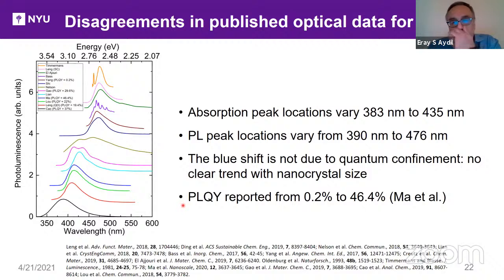So the absorption peak locations vary from 383 to about 435 nanometers. Photoluminescence is also the same. Here is photoluminescence coming from that material and it's all over the place. Again, you cannot explain this by quantum confinement. There is no clear trend with the nanocrystal size. There's a huge difference in the photoluminescence quantum yield reported for these materials, all the way from 0.2% to 46.4% by Ma et al. Most people quote this value to justify that this could be, for example, a material that you can make blue LEDs from.